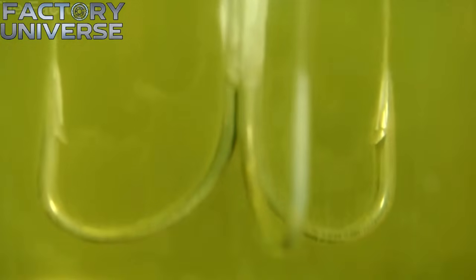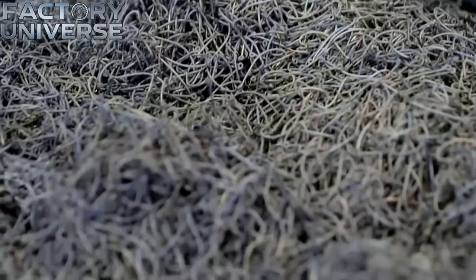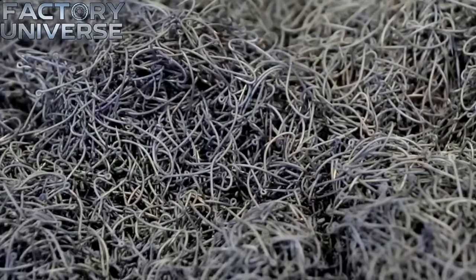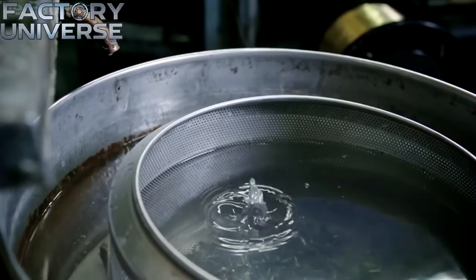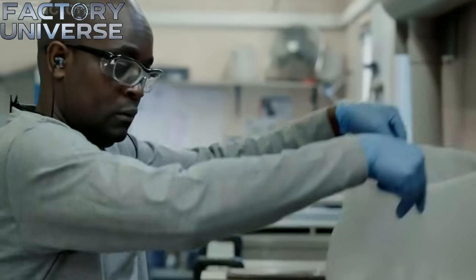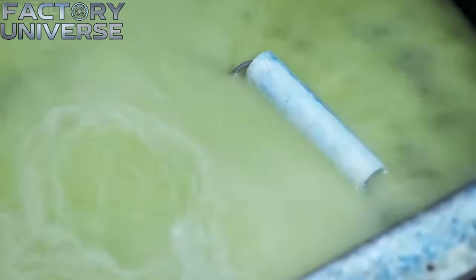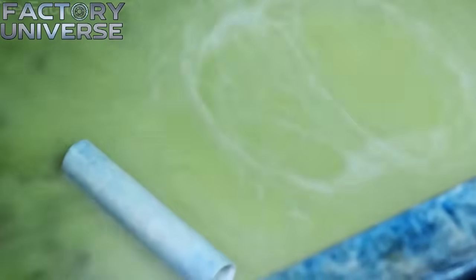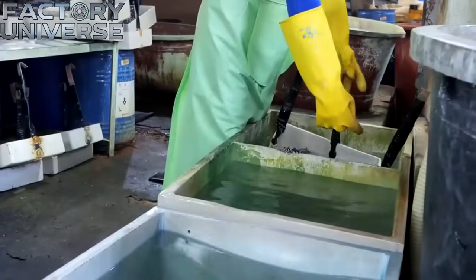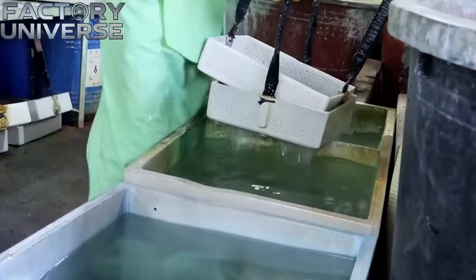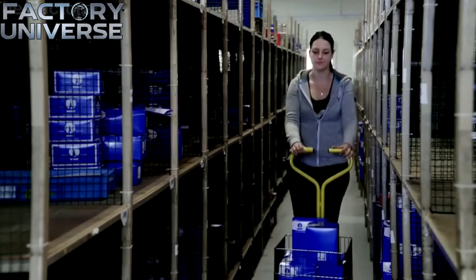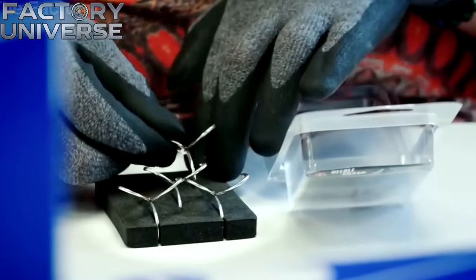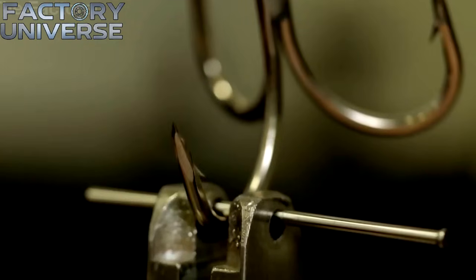15% of each batch, or a similarly strictly defined representative sample, must undergo rigorous mechanical validation before leaving the facility. The hooks first pass through a high-resolution vision inspection system that scans for geometric deviations. Alongside this visual check, samples are placed into a tensile testing machine where force is gradually increased to the design threshold. This test confirms that the hooks will neither straighten out nor fracture when subjected to a heavy load.